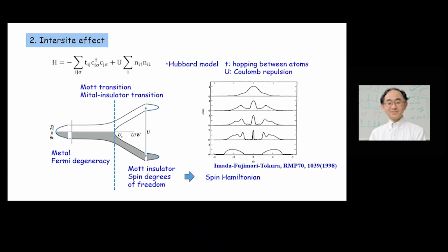Eventually, the Fermi liquid metallic state and the insulating Mott states are well separated. Eventually, you have a very narrow metallic heavy fermionic behavior, and finally it becomes gapped. This central peak corresponding to the Fermi liquid disappears at some critical point. So this is the evolution of the density of states for the single electrons.